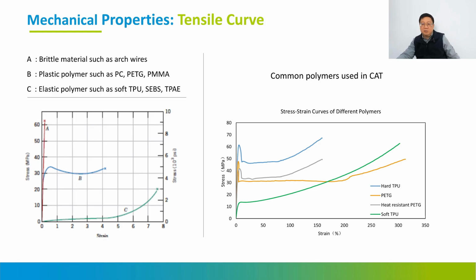You can see the slope of this material. So this slope also shows that it requires different force to stretch this material. So you can see the retainer. They use hard TPU, so its modulus, or its slope, is very high, which means they think they can maintain the teeth in the right position for a longer time. Of course, it's also very durable, because polyurethane is almost one of the most durable materials on the market.